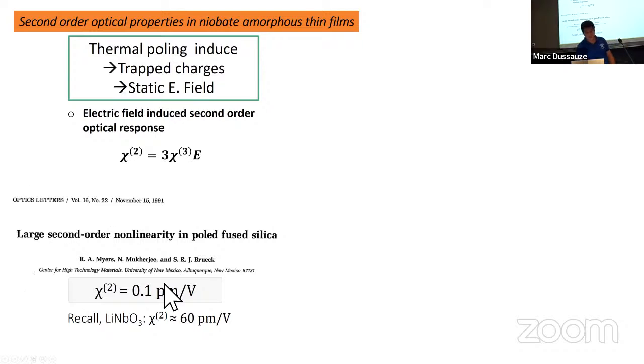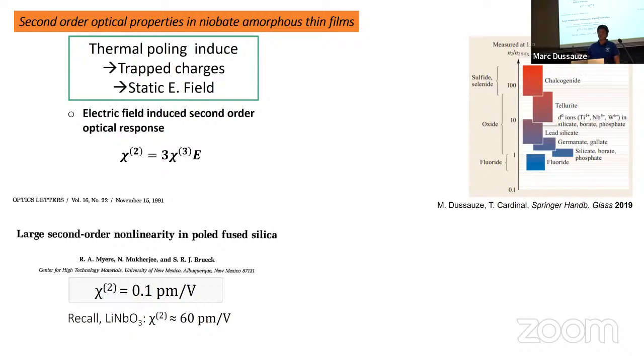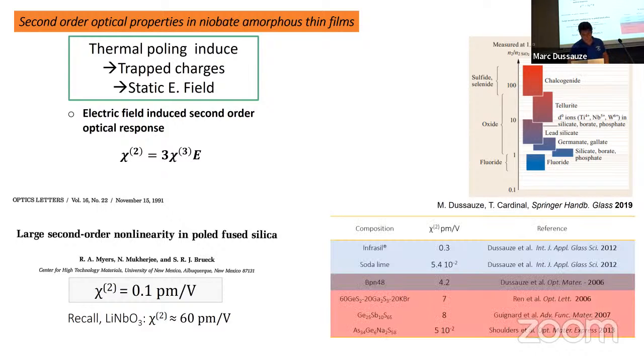People have tried for years and years to improve this Chi2 response inside silica, but it does not work. For this, you need to change the glass structure, change the glass compositions, and try to reach glasses which will obtain very high Chi3 values in order to greatly improve the Chi2 response. So this is what we have done.